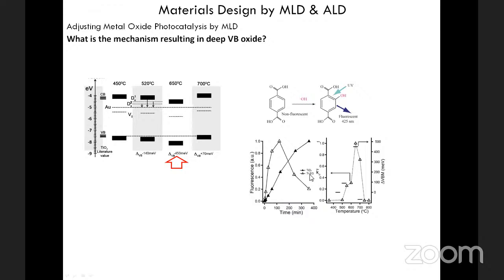However, when we do the same experiment with our films, we see a much sharper increase in the fluorescence, which means that we form much faster the OH radical adduct here. However, soon after, this decomposes and vanishes completely. And here on the right, what you see is a comparison of the rate constants and the shift in valence band that I just showed you here before. And there is actually nice correlation between the two. So it was clear that this downshift has some important thermodynamic and kinetic aspects that we wanted to further understand.